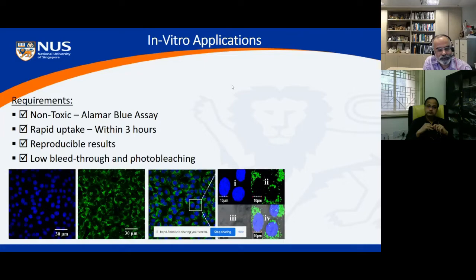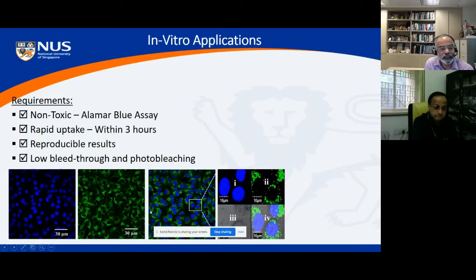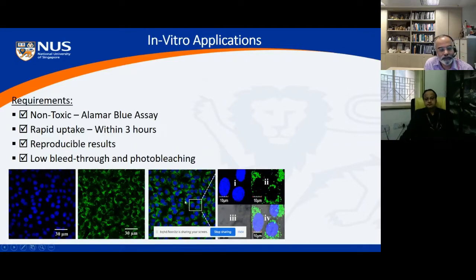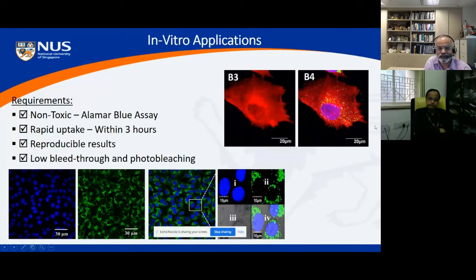So here is a bunch of photographs. So you can actually stay in different areas. The green color is actually from a particle which we introduced. So you see the green colors are actually around the nucleus. They don't enter the nucleus that well, because the nucleus is usually protected much better than the other parts of the cell. So in the nucleus there are no green particles or green fluorescence coming from it, but around it, you can see they tend to accumulate. And you can actually probe much deeper into this. We have done quite a bit of it.